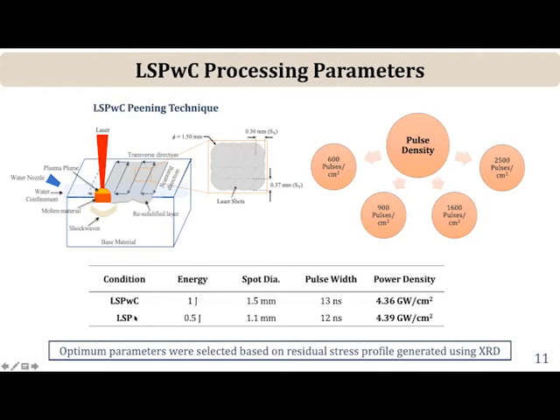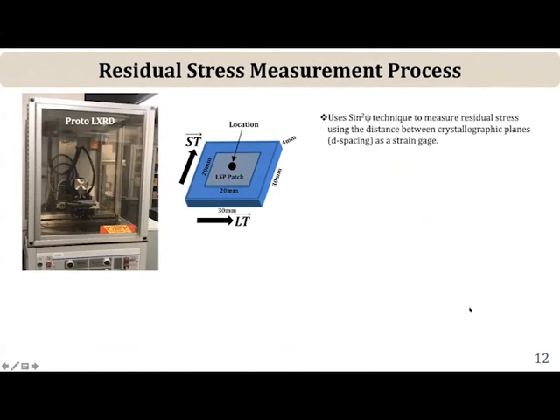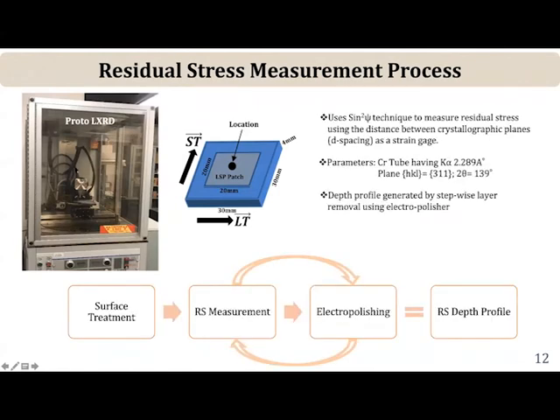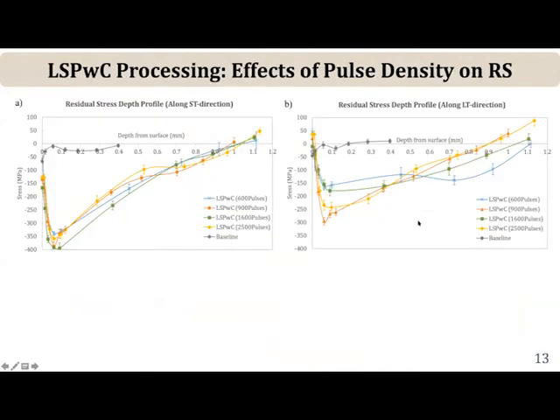Energy is pretty low. The spot sizes are controlled here for these two. So the LSP here is with tape. LSPwC is without the coating, to get approximately the same kind of power density. And these were arrived at based on measurements of the residual stress using X-ray diffraction. So for this, we used the sine squared psi method with a portable XRD system, basically using a chromium tube. The diffraction plane is shown here, 311. And to get the residual stresses to depth, we use electropolishing, remove layers, do the measurement, and then you also account for the stress relaxation and stress gradient due to layer removal, that is taken into account in the software itself.